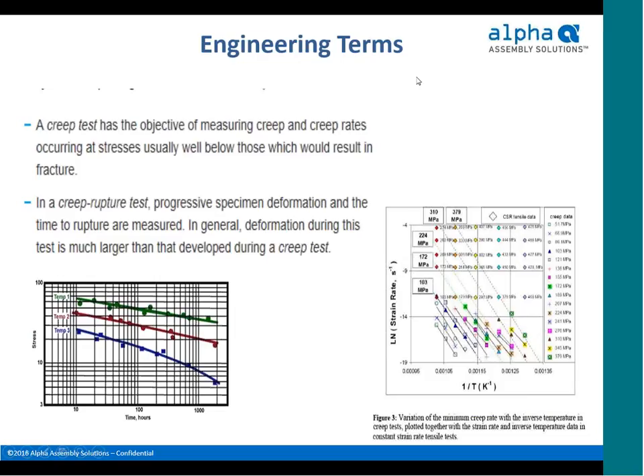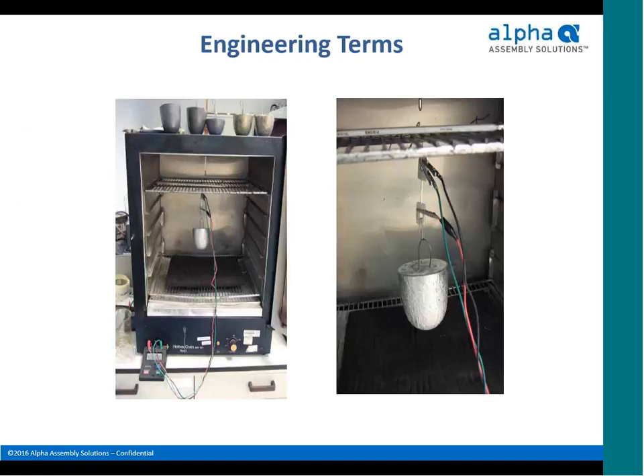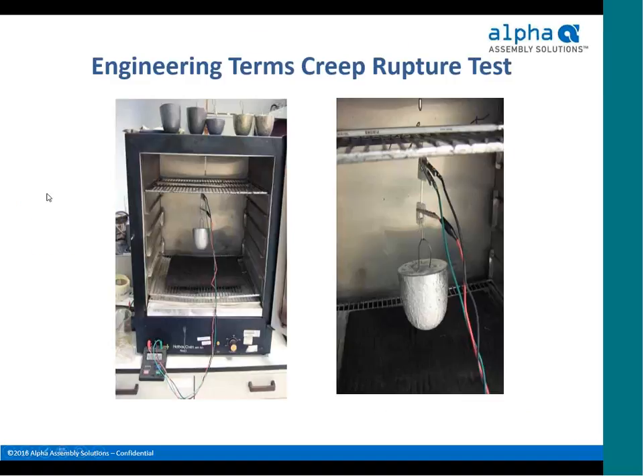So in a creep test, we're going to measure creep and creep rates below those that would result in failure. But in a creep rupture test, you get progressive deformation, and these are going to be using loads that are much higher than would be loaded during a creep test. We're going to try to make the device fail in the creep rupture type tests. So we see a creep rupture test here.